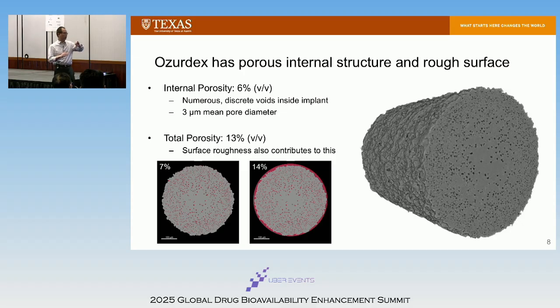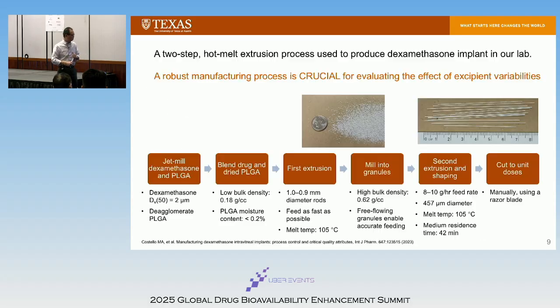We actually like this total porosity because when you make the implants, you use a laser gauge to measure. And the laser actually casts a shadow. That shadow actually factors in the surface roughness. So you can have the same diameter based on the laser, on the shadow, but depending on surface roughness, you're actually getting different materials. But that's what we had.